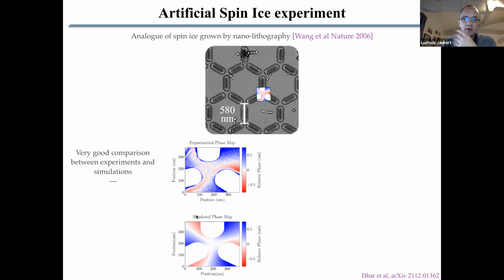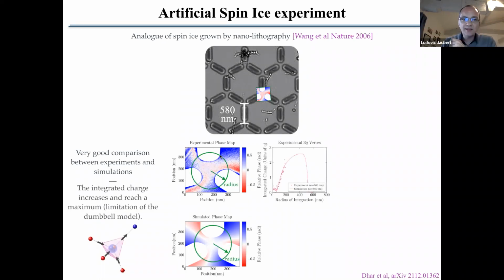And now that we have that, we can draw a radius, because this is where the monopole, the magnetic charge, is, at the center here. And so we can draw a radius around here, and we can integrate the value of this phase map as I was doing before. So here, this center corresponds to the center of the vertex. In the same sense that in spin ice you have the magnetic charge at the center of the tetrahedron, here you have it at the center of the vertex. So you have a magnetic charge at the center here, or possibly at the center here, and so on. In this case, for this specific configuration, you have a magnetic charge at the center of this vertex that has been measured. And we have the experimental phase map.